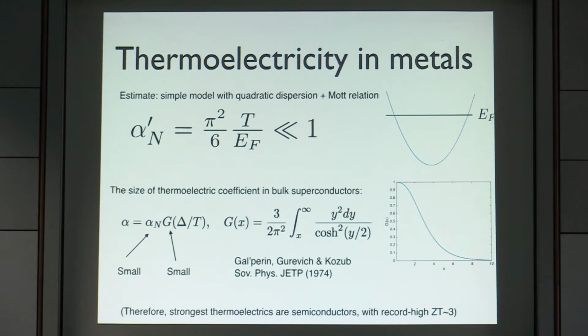So how about superconductors? First it was thought that superconductors don't have any thermoelectric effects. Nowadays it's known that they do have thermoelectric effects, but they are even smaller. The typical estimate of the thermoelectric coefficient in superconductors is basically this metallic thermoelectric coefficient times some factor G, which counts the number of quasiparticles in the system. So this G is always smaller than 1. This means that if you want to have a large thermoelectric effect, you should rather use semiconductors and not metals.